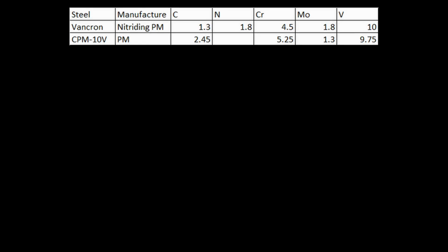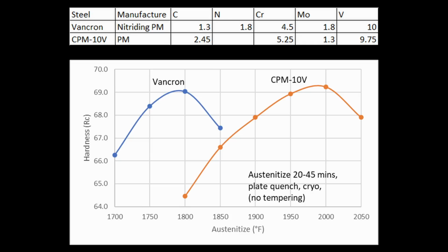All right, one more example. We're going to compare Vancron and CPM-10V. So again, two steels that aren't compared that often, but they're essentially the same thing, but one has a bunch of the carbon replaced with nitrogen, which is, of course, the Vancron. So the Vancron austenitizes from a much lower temperature, the same thing we saw with LC200N and BD1N. But it peaks at around 69 Rockwell as quenched with cryo, just like the CPM-10V does, even though the Vancron has a bunch of nitrogen.